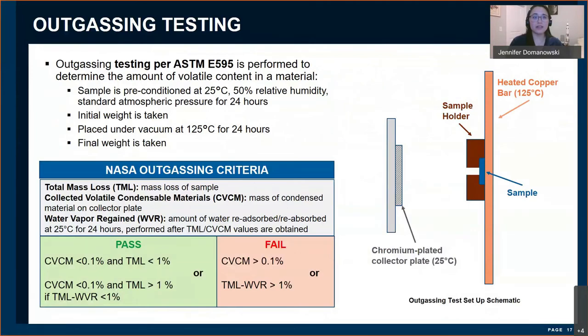To test for outgassing, we follow ASTM standard E595. And so this test determines the amount of volatile content in a material. And NASA has actually developed a set of outgassing criteria to help provide guidelines on whether or not a material should be used in space, whether it passes or fails. And there's actually an entire NASA outgassing database that's available to the public. So we collect this data and store it on there, and then you can access it. And my branch at NASA Goddard performs nearly all the testing for this database, and we're also the ones responsible for maintaining it. So that's pretty cool.